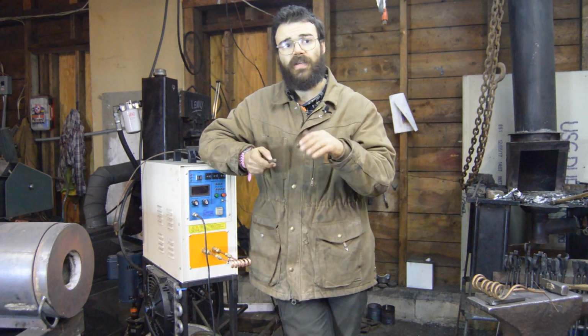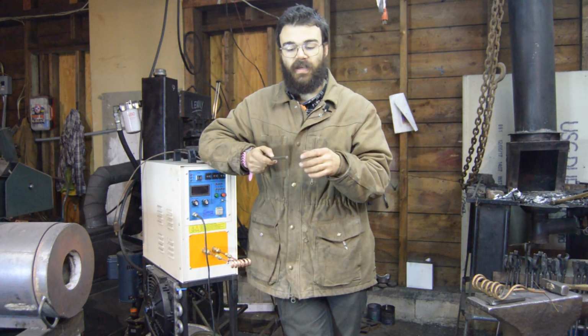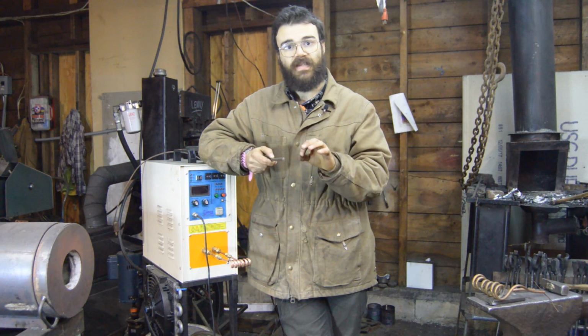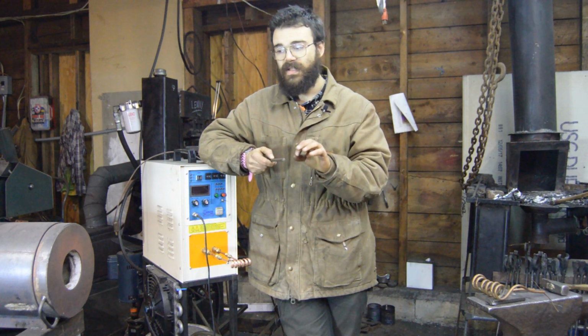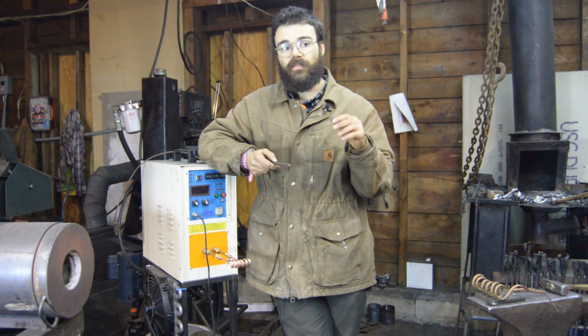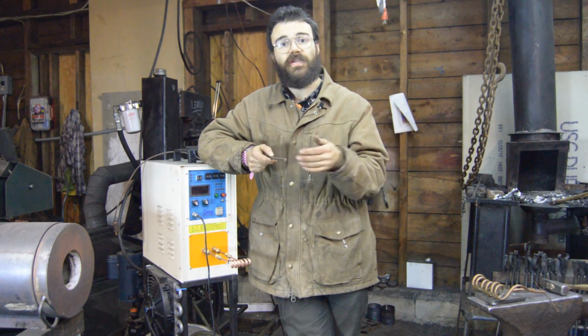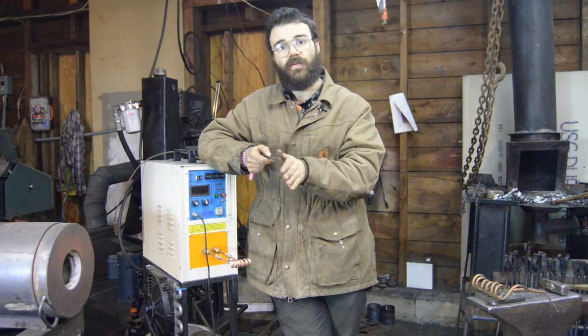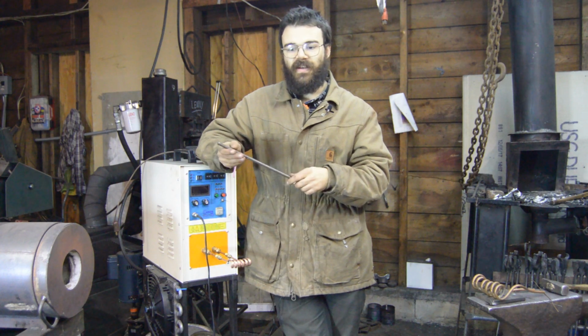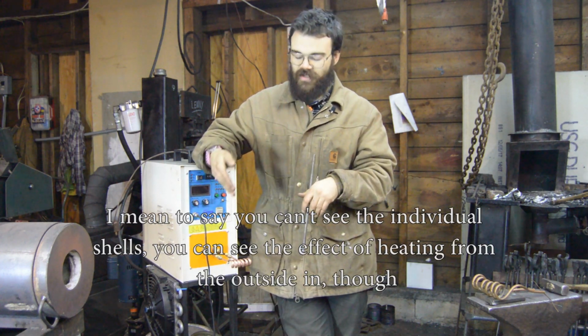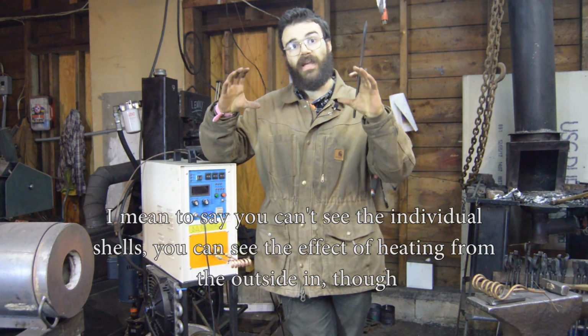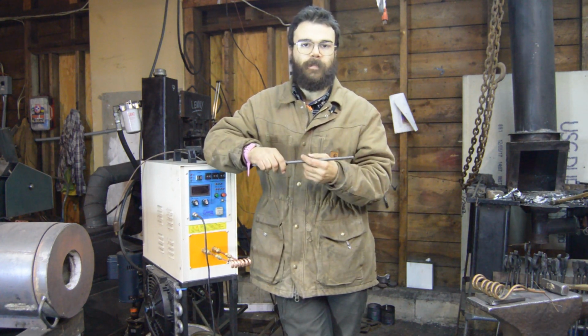This happens more slowly, again because of the relative lower flux density on the inside of the coil of the magnetic field lines. And it's also slightly increased by the fact that there is conduction through the material from the hot shells to the cold shells. So it's not a discrete process, like you can't actually see it, but you will see that the heat travels from the outside to the inside, and that's why.